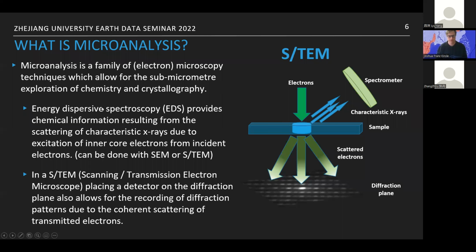We'll talk more about the results of this, but these are characteristic of the material you're looking at. So different atoms give off different X-rays. And by looking at relative proportions of those X-rays, we can make quantitative estimates of what's in the sample. Similarly, when the electrons pass through a very thin sample, they can diffract, which means that if we place a detector on the diffraction plane, we can record diffraction patterns. And this second one is the second bit of the crystallography that we will hopefully look at.